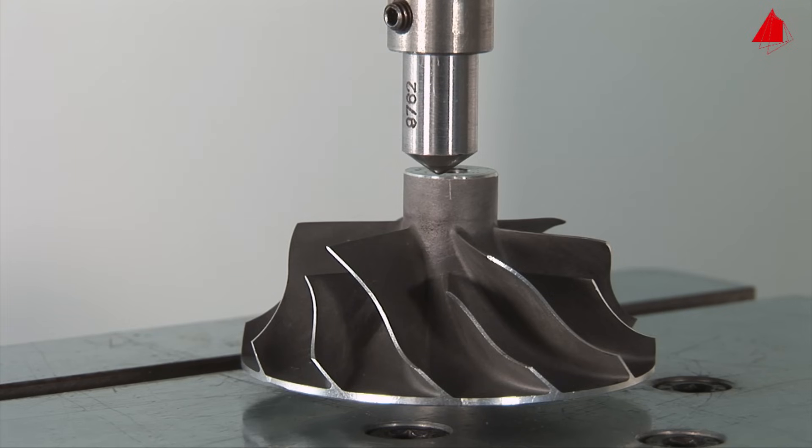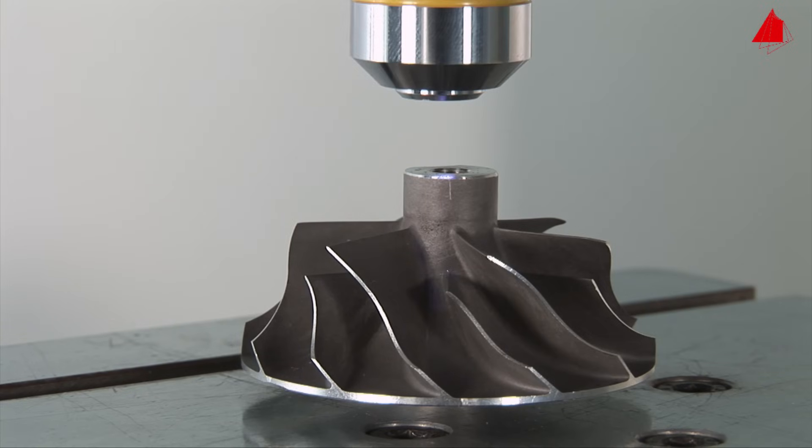After pushing the start button, the diamond pyramid pans down and carefully touches the test piece surface. The test force slowly increases to its specified value. After holding the test force constant for a certain time, the indenter lifts again, pans back, and the microscope lens resumes its former position.